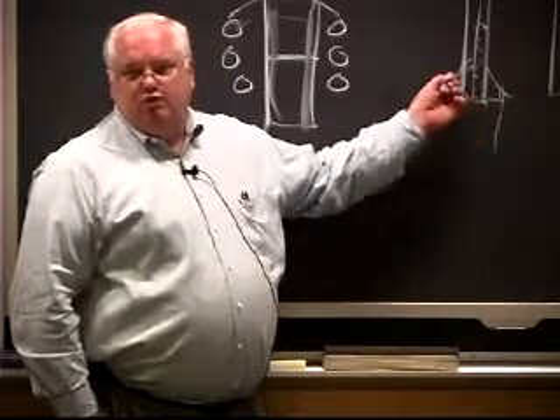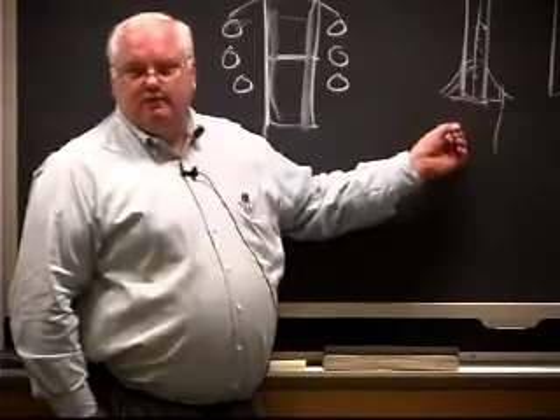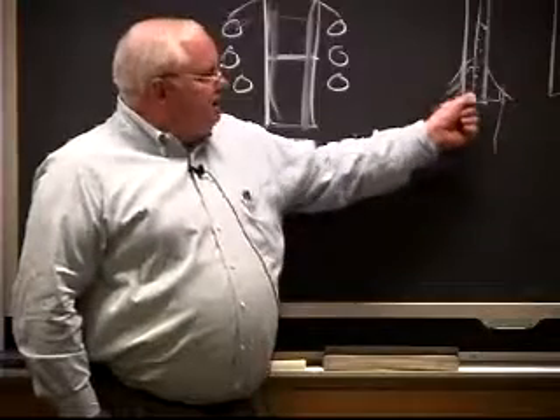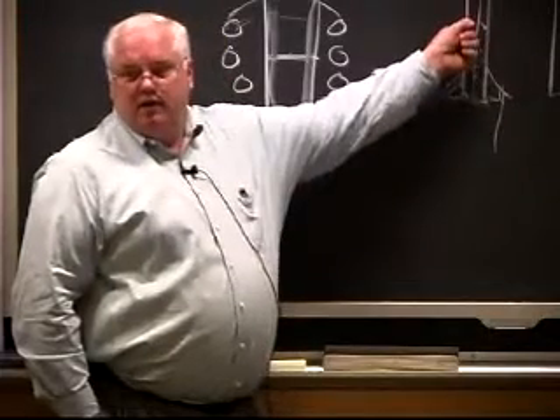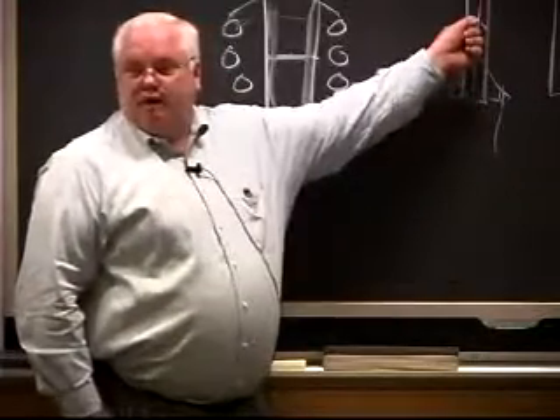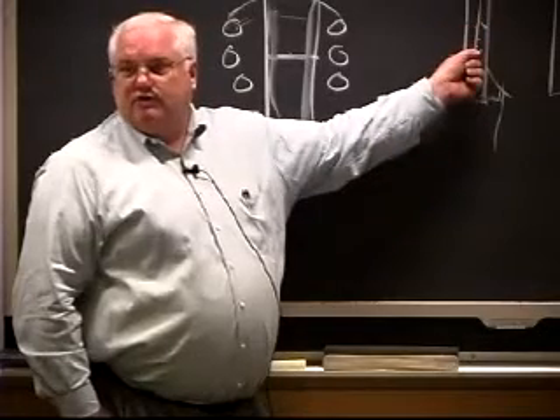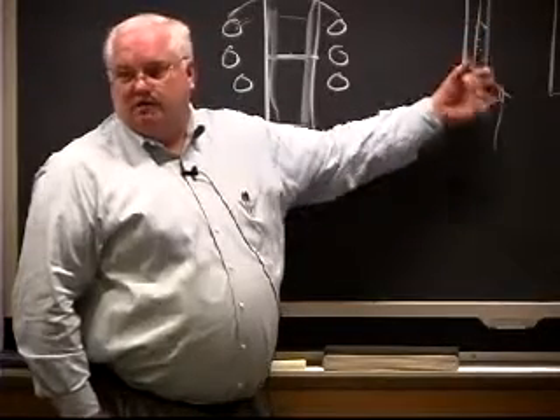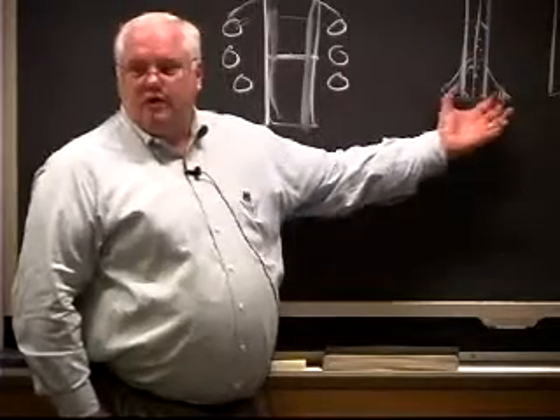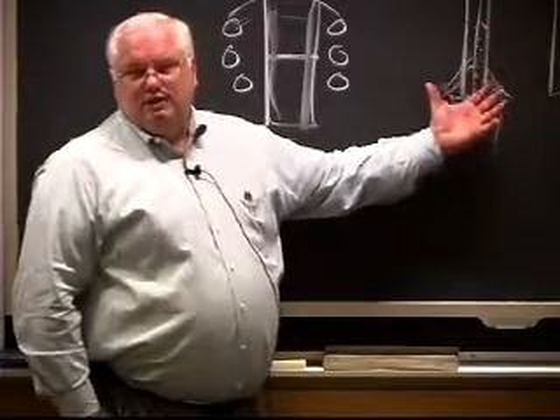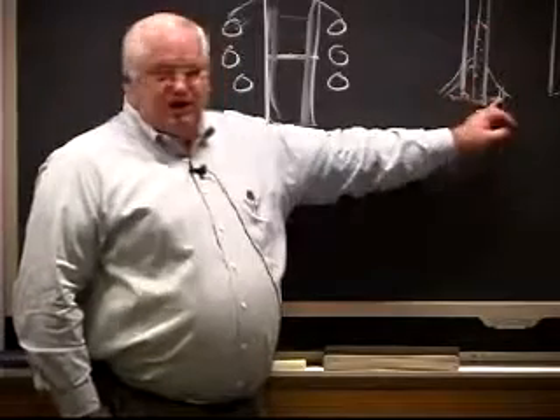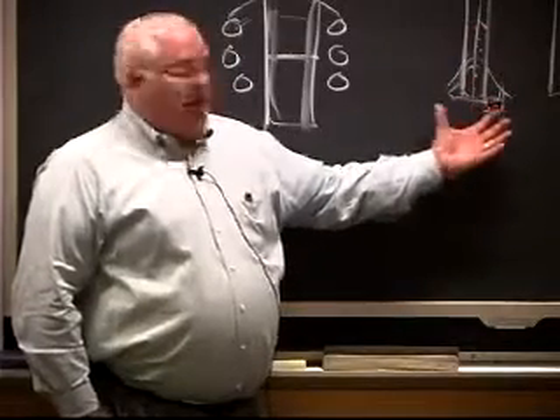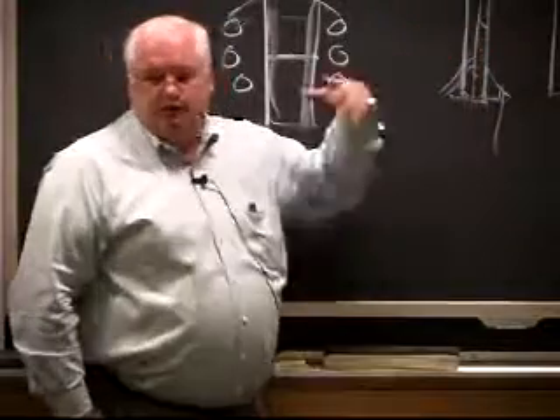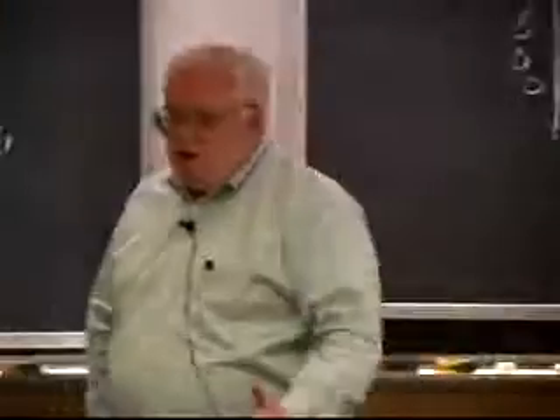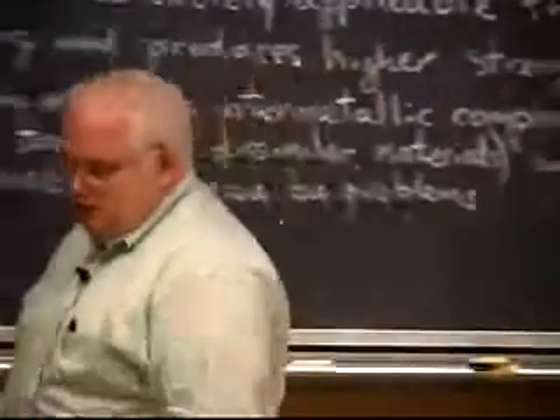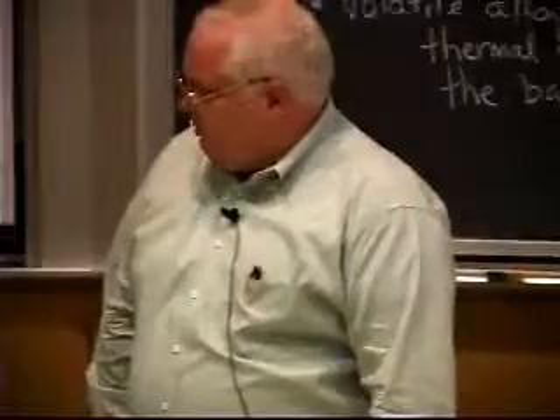The solution was to braze in a temperature gradient. If you braze in a temperature gradient and it's hotter down here than it is up there, then the nickel's not going to flow up there. It's going to stop because it's going to solidify, right? So we were able to make the joints we wanted to make even in the porous carbon by doing it in a temperature gradient. Essentially we went to induction brazing and just heated up the bottom here and not the top. Before we were heating the whole thing with a great big flame, and we were getting everything fairly uniform and hot, which was not what we needed in that particular case.